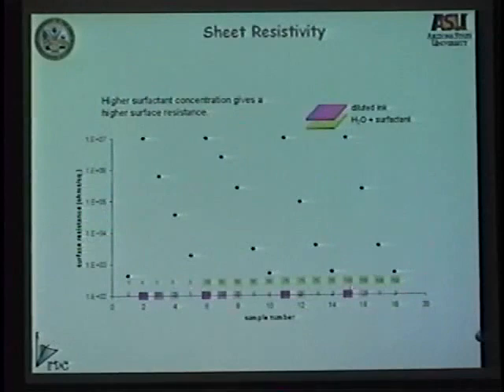So with that said and done, you could see that this looks like they're scattered all over, but if you put your eye on the sets, set by set, you could see a linear progression for 100% water, and then variation in the density of printing of the surfactant. You could see a linear progression, and that's what you expect from sheet resistivity. So we can go from this is the 0, no printing at all, so the PEDOT is as received, it's about 300 ohms per square.